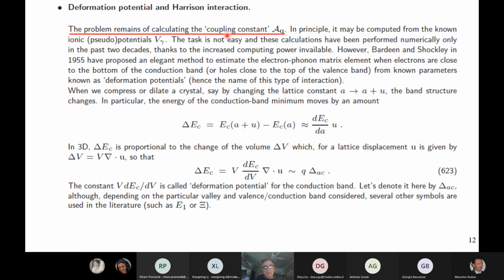At the time, the problem was a little more complicated. As I mentioned, I think last week, the electron mobility in intrinsic silicon was supposed to be something of the order of 350 centimeters squared per volt second, which is about a factor of 5-ish smaller than what it is. So the crystals were not particularly good. Nevertheless, the idea that Bardeen and Shockley had in 1955 was,